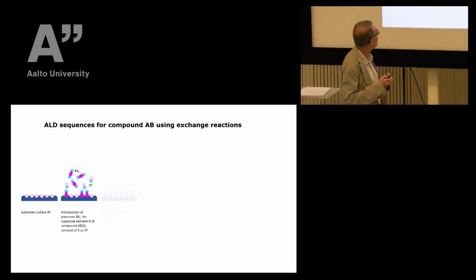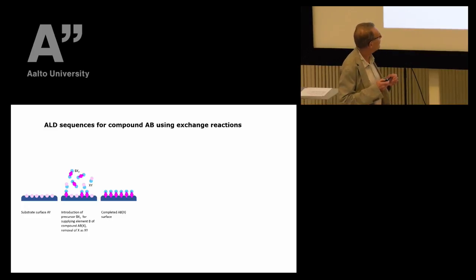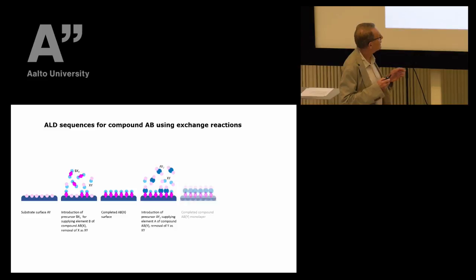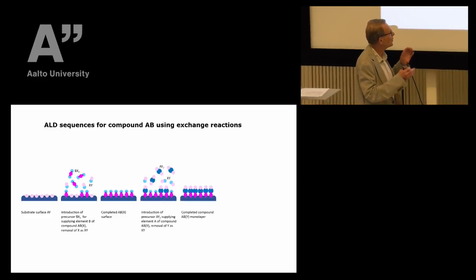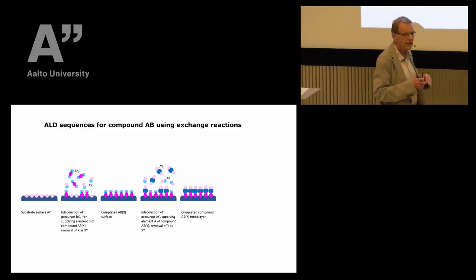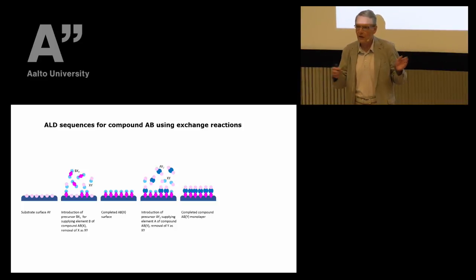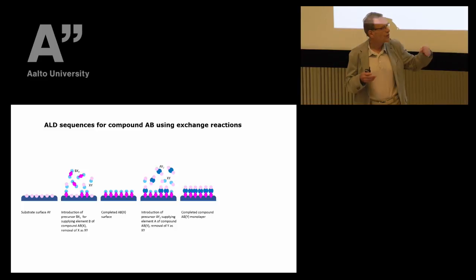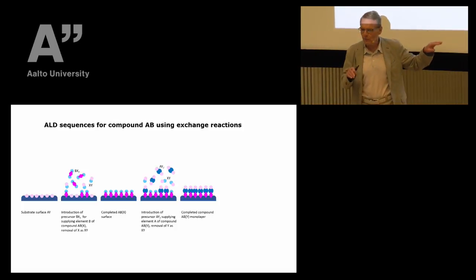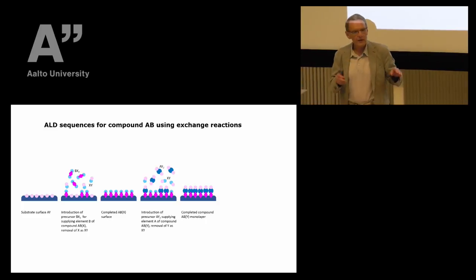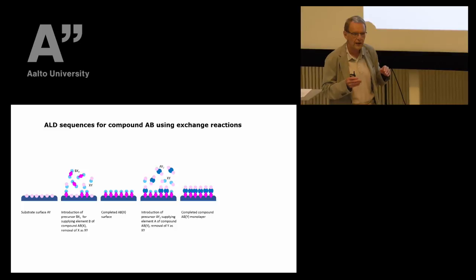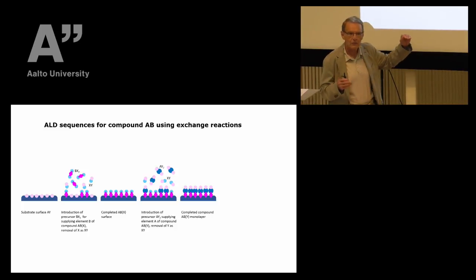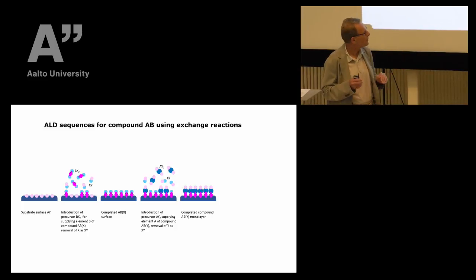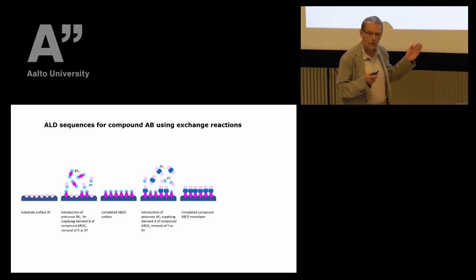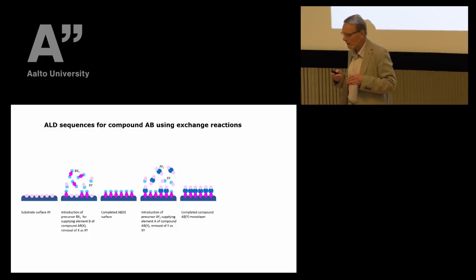As I stated, we prefer using compounds of the final compound, and there are a lot of tricks that can be used to find processing conditions that fit with the other parts of a production line, for example. With semiconductors, very often we must not increase the temperature of the substrate too much in order not to disturb the other structural parts of the devices, so that it's advantageous to find highly volatile source materials and very reactive reactants, so that we can decrease the temperature of the growth, so that finally, although the basic idea is very simple, it leads to very demanding chemistry.